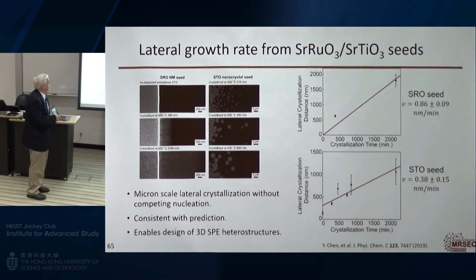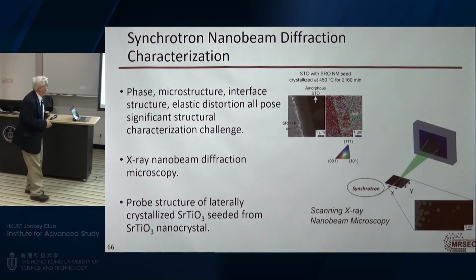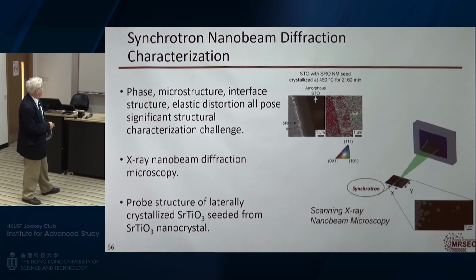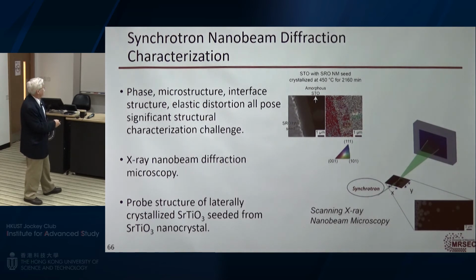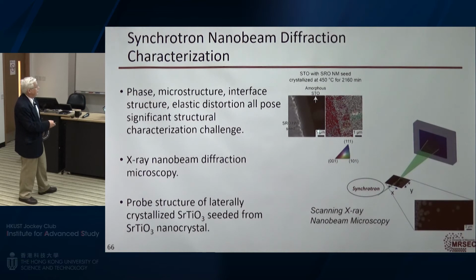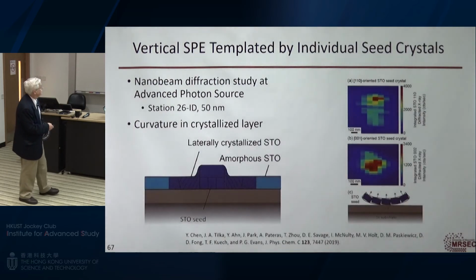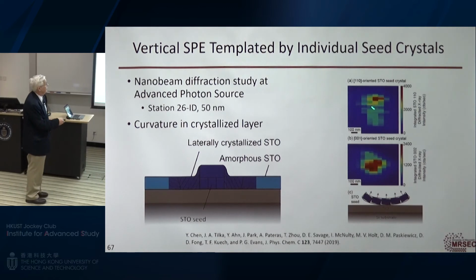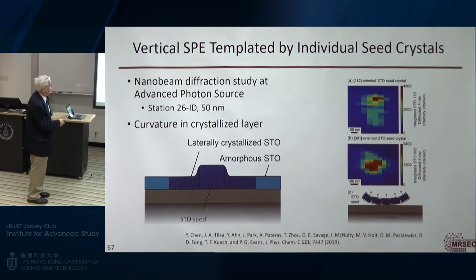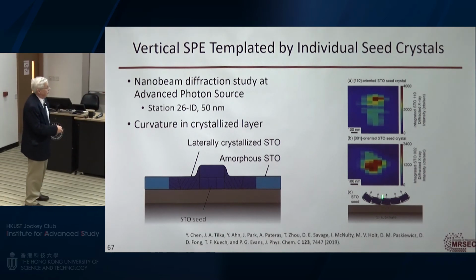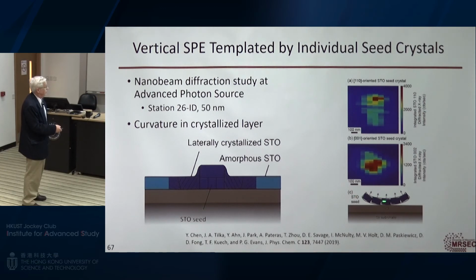So there's a variety of ways that you can use interface and surface kinetics to modify or form metastable materials into interesting structures. I just wanted to point out we have access to a synchrotron where we can do nano diffraction and actually look at the crystallization front as it's moving across in real time, and we're building that capability. So we can watch in diffraction the formation and the transition from the amorphous to single crystal material. And we've started doing some of that work, and you can see the diffraction pattern, this is on the order of a couple hundred nanometer beam size. We can get X-ray diffraction. We can see that in this particular case, there was some mosaic spread in the crystal.